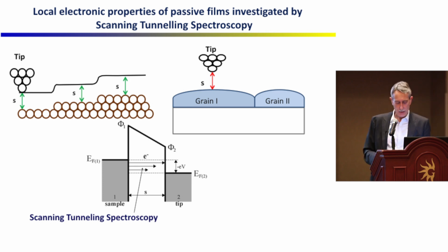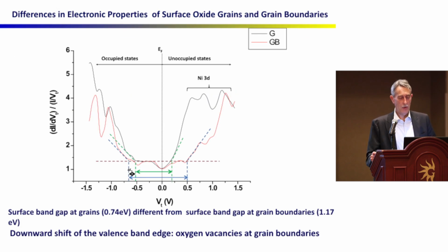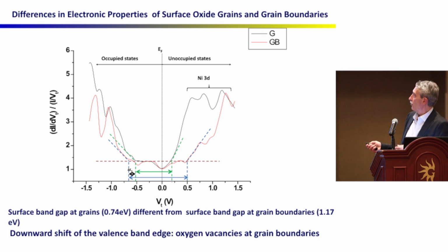So we did that, and we started with nickel because we have good control of the structure. So this is typically what we get. After some mathematical treatment of the data, we get the density of electronic states as a function of energy. So it's not the electrode potential here, it's the energy. We have the Fermi level here, and we have the conduction band starting here, and the valence band.